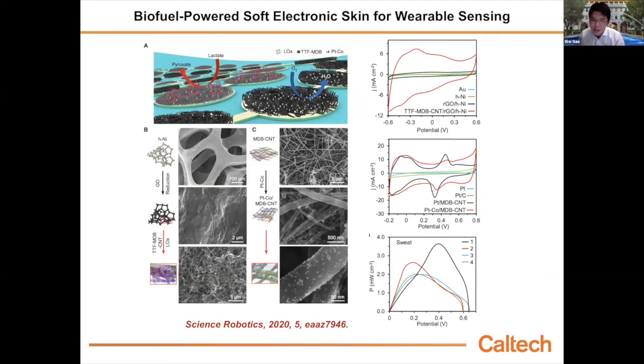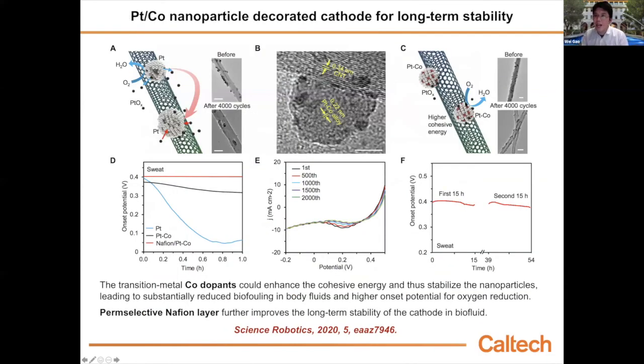Based on this, we can harvest energy from our body fluids, from untreated sweat, at a power of 2 to 3 milliwatt per centimeter square, several milliwatt per centimeter square. It's very high already. We also show that not only can we get high power, our technology can also deliver very high stability, because typically biofuel cells suffer from poor stability.